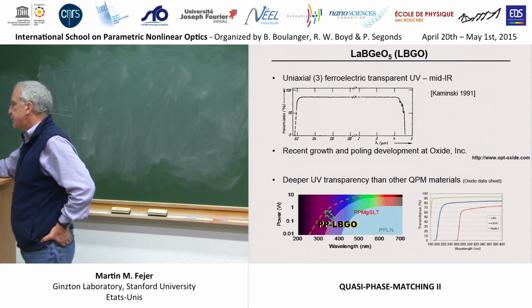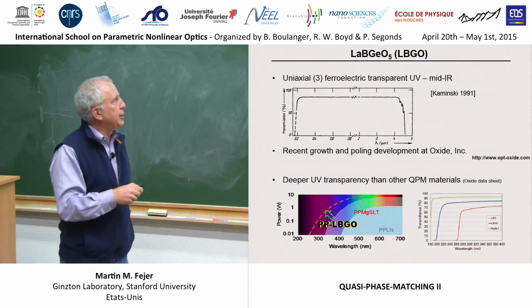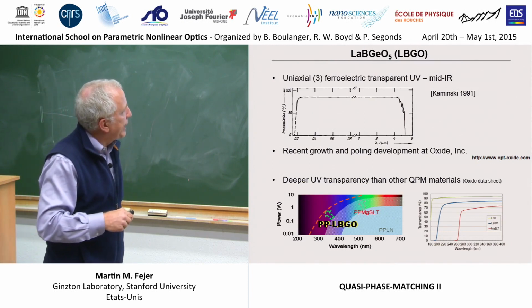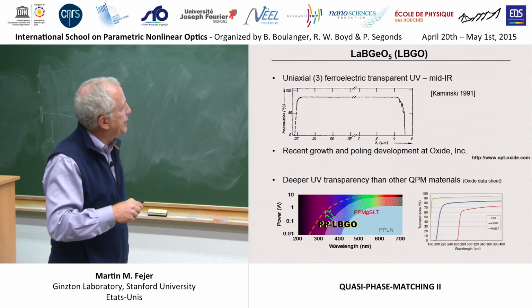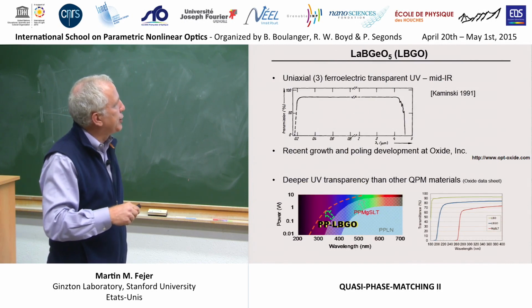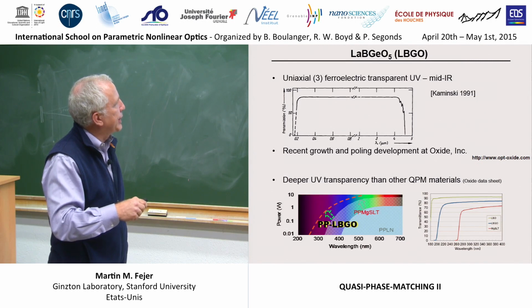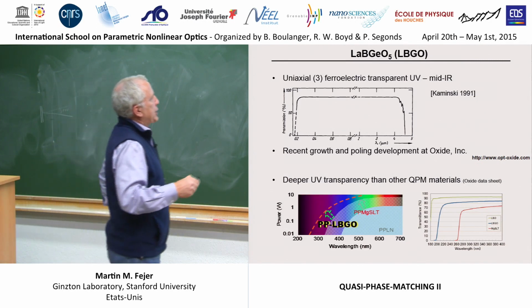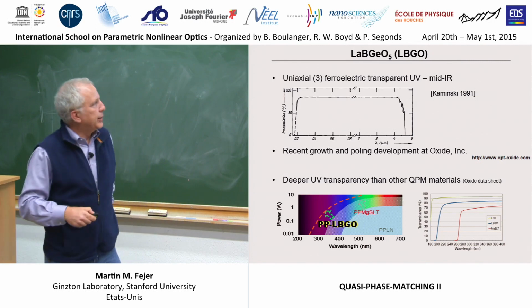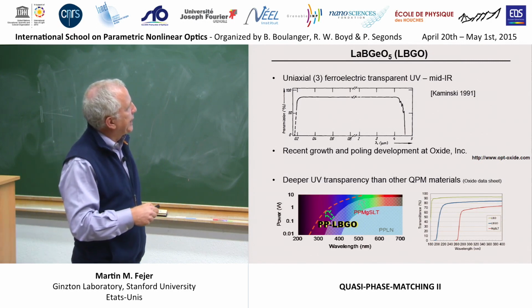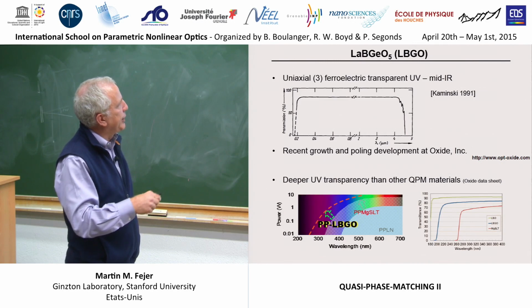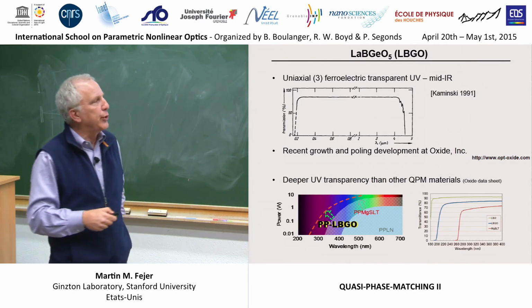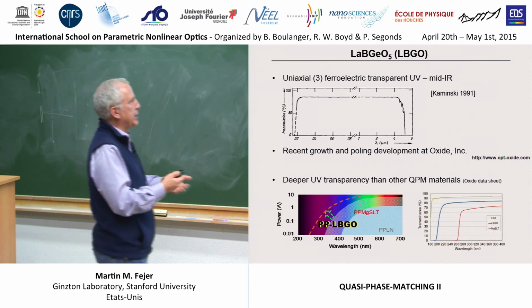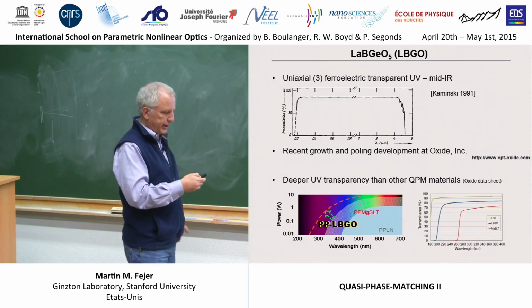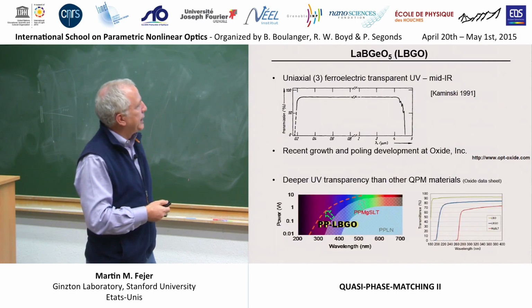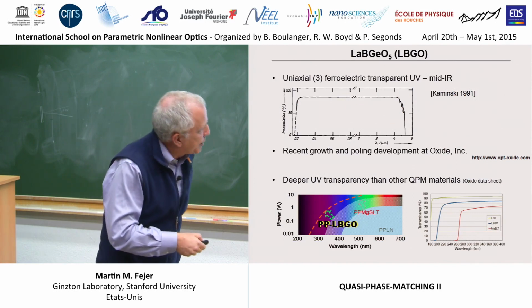So this is a transmission curve of lanthanum borogermanate. And you can see that the fundamental edge is shorter than 200 nanometers, and it has decent transmission to just about 200 nanometers, 210 nanometers, whereas all the other crystals are kicking out somewhere in the vicinity of 350. So you really have access to third and maybe even fourth harmonic of the neodymium YAG laser using this material. And this is a close-up of that absorption edge.